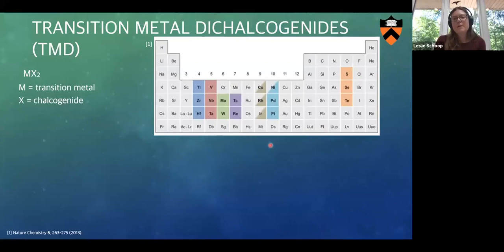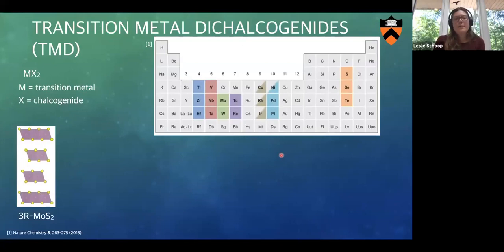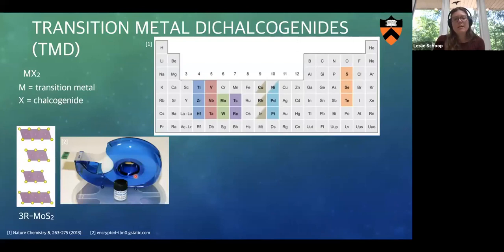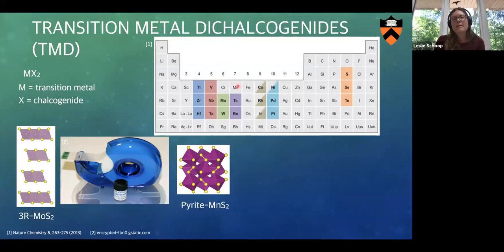table here of these elements which form layered dichalcogenides. And you might know a famous example is MoS2, which has this layer structure where you can put scotch tape on top and you get a monolayer. However, these are the transition metals of interest for magnetism, and these don't seem to really form layered transition metal dichalcogenides. So for example, if you look at manganese, what it does with sulfide, it makes a cubic pyrite, and good luck putting scotch tape onto this crystal structure and getting it to the layer.